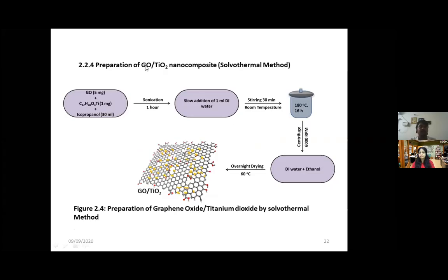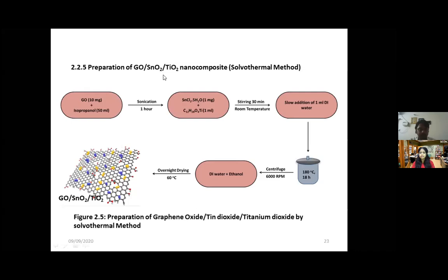And the third sensor material is graphene titanium dioxide. The same procedure, the change is we use the titanium dioxide precursor here, that is TTIP, titanium tetraisopropoxide. And the fourth sensor material is a ternary nanocomposite. The first three are binary, this is ternary. So we use both the tin oxide and titanium dioxide precursors here for the preparation of this ternary nanocomposite. The fourth sensor will be addressed as GST.